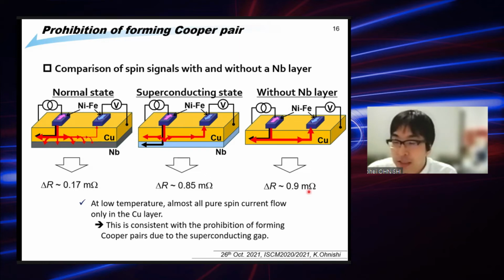This is nearly the same as the 0.85 milliohm in the superconducting state. This result indicates that in the superconducting state, almost all pure spin current can flow in the copper layer, then reach the detector.